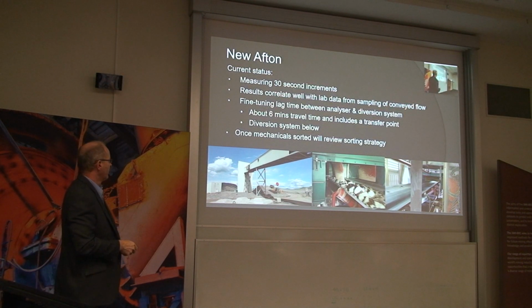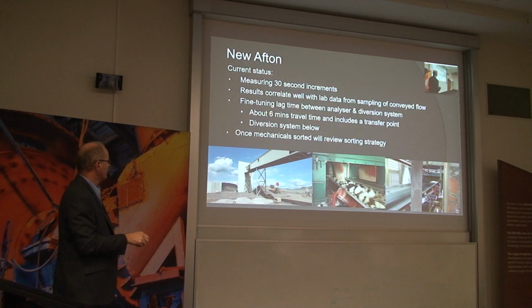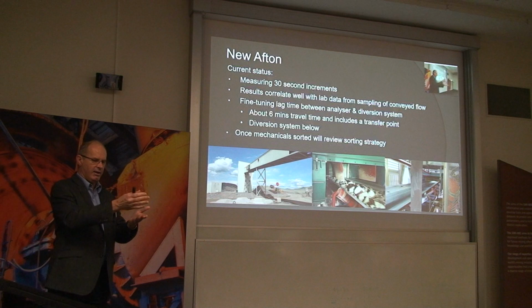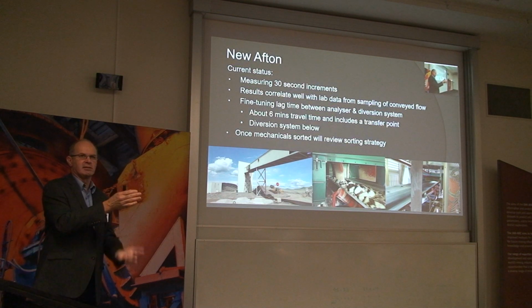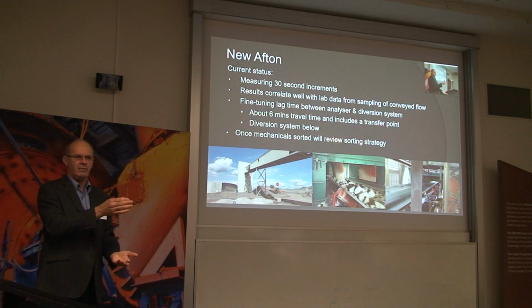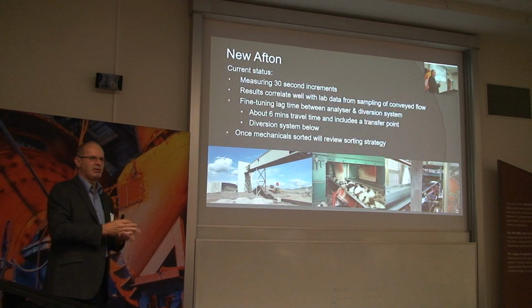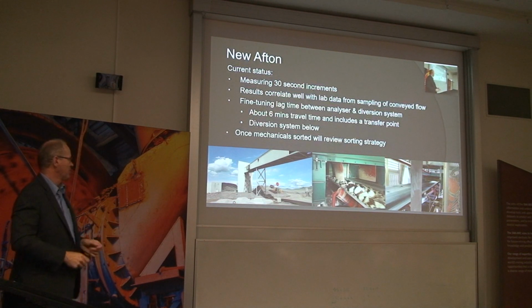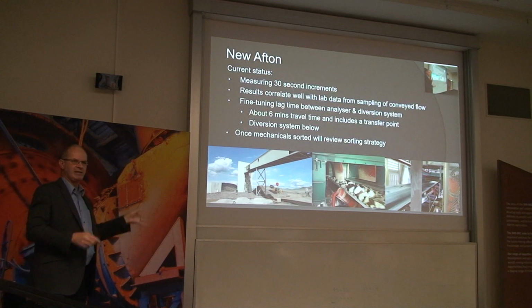Okay, so you can see the plough here. That plate doesn't move, but when they want to divert for 30 seconds, the belt is lifted up, flattened out, material is ploughed off for 30 seconds, and then it drops down again. Whether that actually happens within a second, I don't know. So they're still fine-tuning their system.